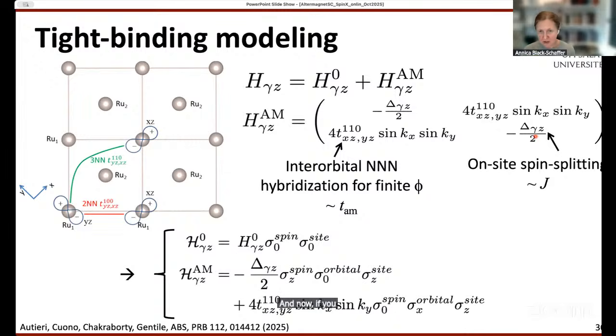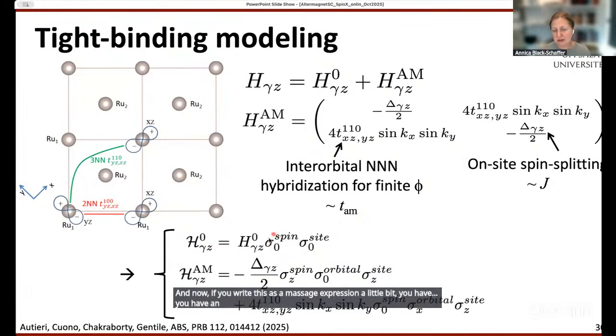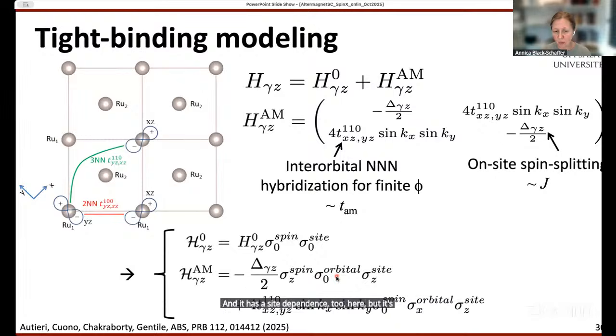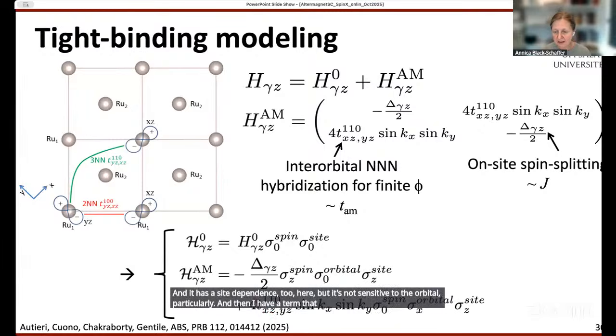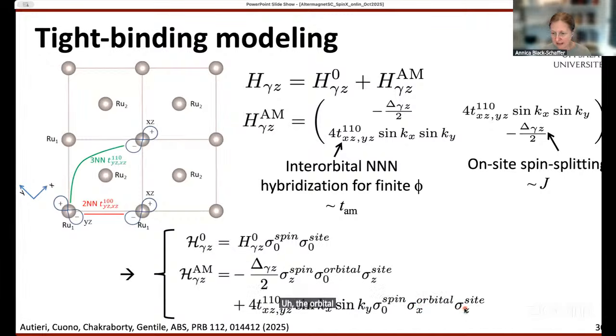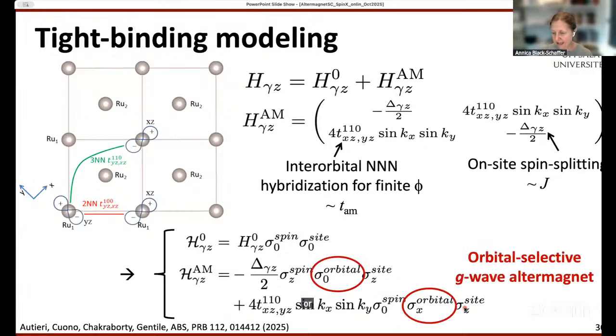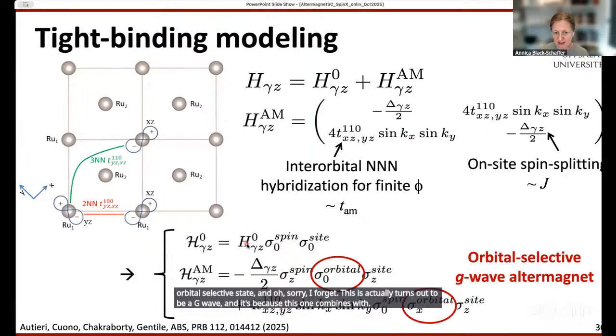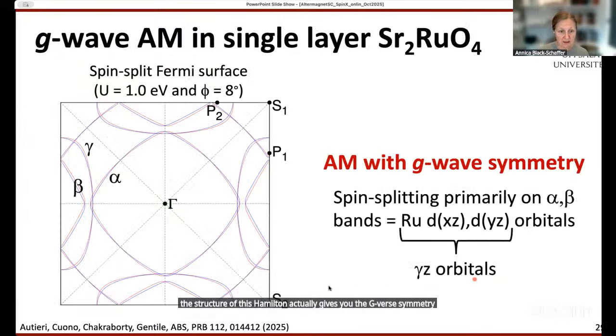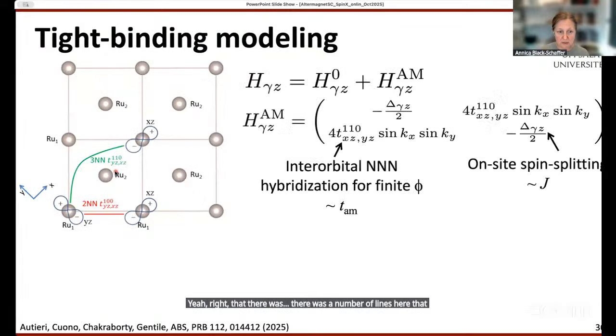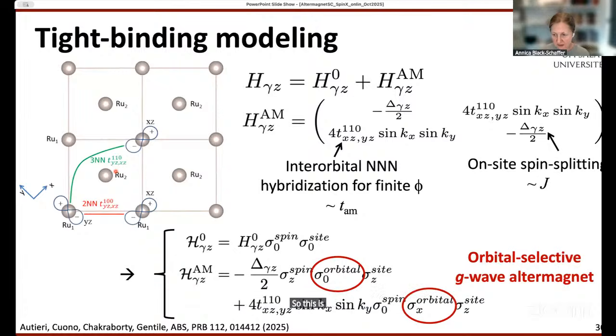And now, if you massage this expression a little bit, you have an initial Hamiltonian that is not sensitive to spin or site, but you have an altermagnet part that comes with this rotation angle, which has a term that's sensitive to the spin. It has a site dependence too, but it's not sensitive to the orbital particularly. And then I have a term that is the hopping that is sensitive to the orbital, with another Pauli matrix and the site. So I have this orbital selective state. This actually turns out to be a g-wave, because the structure of this Hamiltonian gives you the g-wave symmetry. You probably saw that here, right? There were a number of lines here that made it a g-wave state. So it doesn't give you altermagnetism in all orbitals, but just a few.